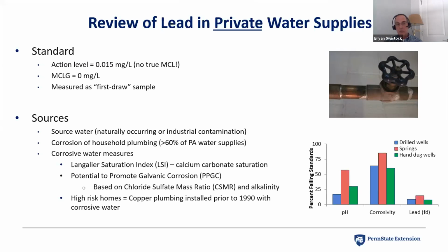Alkalinity is also still important here, but chloride concentrations in relation to sulfate are really the main issue. And as I mentioned, high-risk homes tend to be those that have metal plumbing, specifically copper plumbing with lead solder, as is shown in the picture up there in the top right, that was installed prior to the regulations that went into effect that removed a lot of lead from solder, which took effect in the late 1980s.